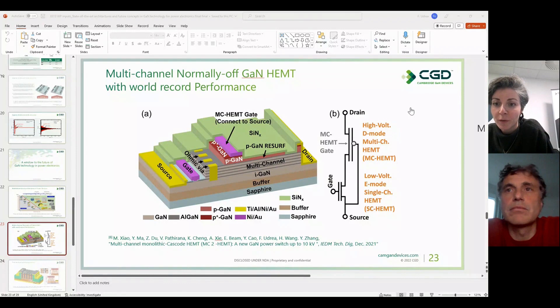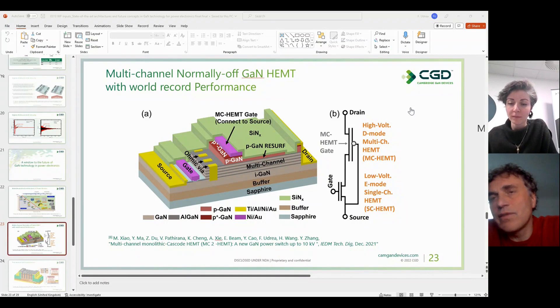From Ortiz Gonzalez Jose: have you characterized temperature dependency of gate leakage current? Yes — gate leakage increases with temperature as expected, but is well under control. Our data shows gate leakage at higher temperatures as well. From Khalid Saad: how is the performance with current-source gate drivers? The sense HEMT has a resistance sensing load at the source, so it is not a perfect scaled reproduction of the power HEMT at all currents — accuracy is better at lower currents and less accurate at higher currents. For applications where current goes to zero, it is a perfect solution.